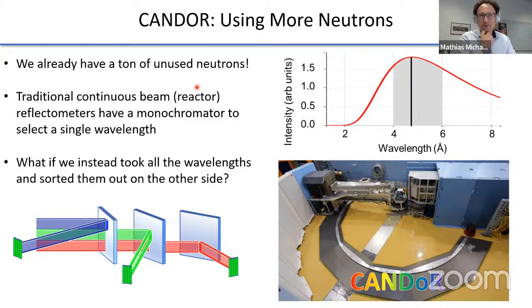Right. So I think this is a result of poor pacing on my part, in that I ran out of time to really explain how CANDOR works. So, the difference between spallation sources and reactor sources. I work at a reactor source for neutrons, and that means we have a continuous stream of neutrons coming in. At a spallation source, none of this really applies because they use time-of-flight measurements. The time-of-flight measurements give you all the energy resolution you want, because you have very precise timing on the neutron arrival.